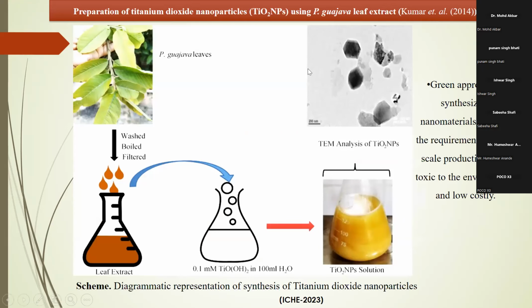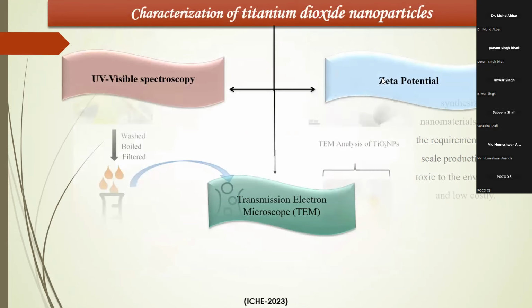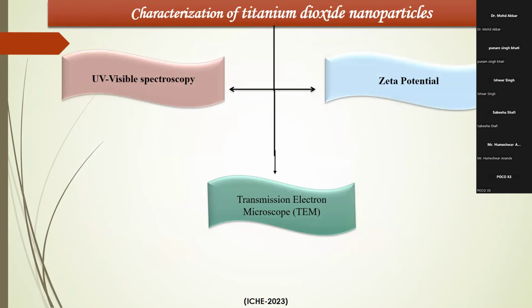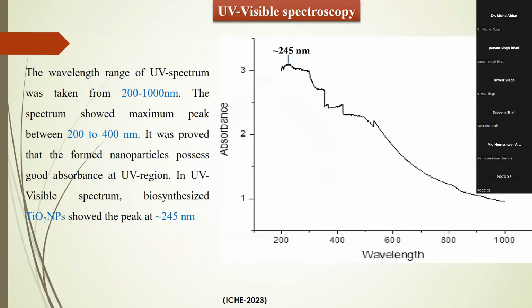Here I prepared titanium dioxide nanoparticles by taking guava leaf extract as a reducing and capping agent, following Kumar et al. 2014. And the preparation of titanium dioxide was confirmed using UV visible spectroscopy, zeta potential, and transmission electron microscope.